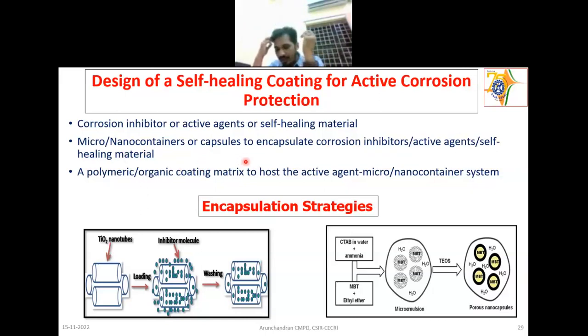If you see what kind of capsules, the capsules can be polymeric as well as inorganic. With the polymeric capsules, people have used especially urea formaldehyde, one of the earlier capsules, formed with various sizes, 50 microns to 150 microns, 400 microns, 500 microns. And then later come the nano capsules.